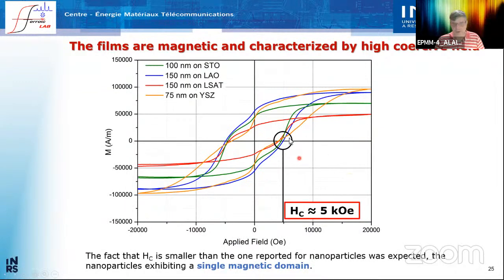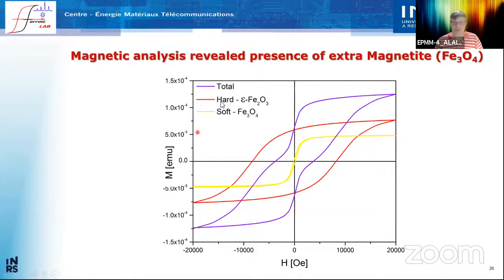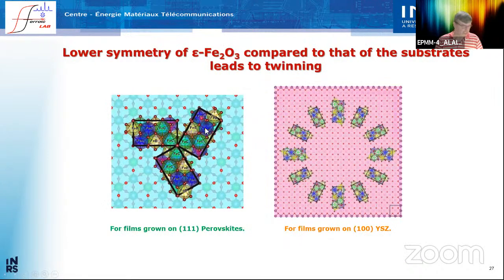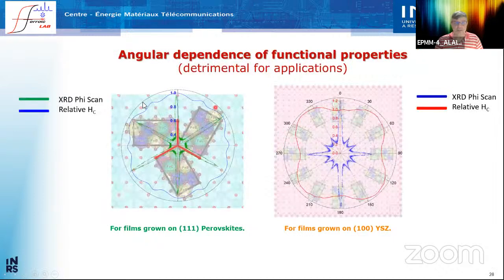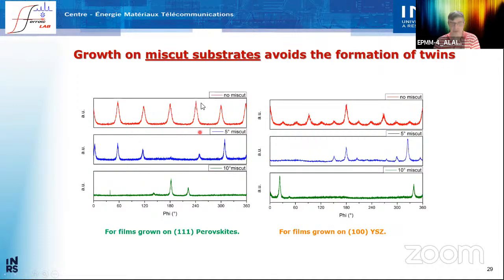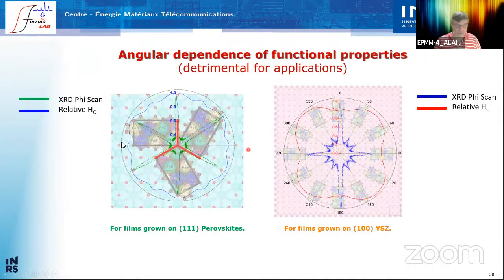That is for a nanoparticle, it's a little less, because for a magnetic nanoparticle, you have a single domain. You have this pinched loop, which can be very well explained by a very, very small amount of magnetite within the Fe2O3. But as I said, because of this very complex epitaxial relationship, this material, which was strongly anisotropic, is now having a lot of twins, and the anisotropic properties are actually becoming pretty isotropic, which is not good.